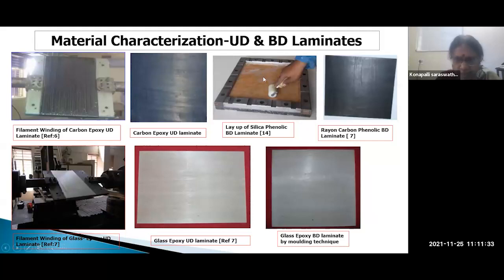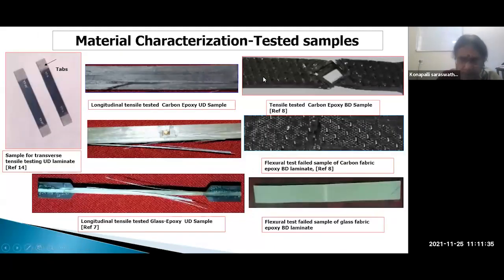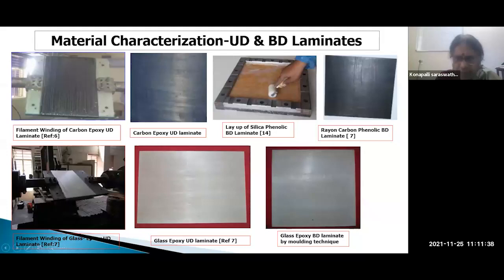And for bidirectional, it is just a die plate with spaces, and then we put the required number of layers and punch plate is put. That is how bidirectional laminates are made. This is rayon carbon phenolic bidirectional laminate used for thermal characterization. So this is how material characterization is carried out by making UD and BD laminates. A lot of ASTM standards are there to perform these tests, and that we get the properties. Those properties we input for our mechanical and thermal design.